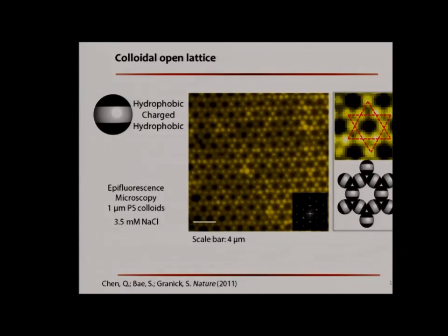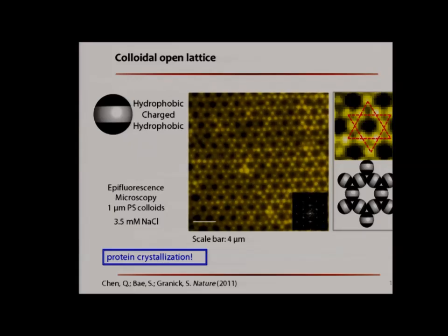And this new structure really invites new views. You can see it as a porous filter with two populations of pores, not only different in size but also different in pore surface chemistry. You can even see analogs with protein molecules. The crystallization kinetics here is a two-step process, which has been reported before in protein crystallization. And we regard it as more than a coincidence because the protein molecules studied also have a patchy surface, just like our artificial patchy colloidal particles.